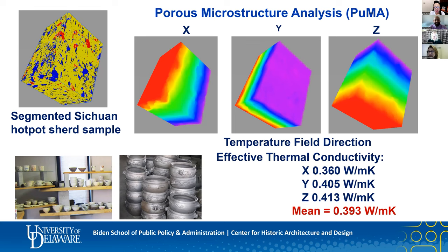One is that ancient ceramics are always going to have more variability within a production run and within a site, certainly, and even among different potters at one site compared to modern mass-produced wares made in a factory that can be very consistent. And modern ceramics also make use of various synthetic ingredients available today, whereas ancient ceramics are made with natural ingredients such as just clay and minerals and straw, that sort of thing. And also modern kilns and furnaces can achieve higher temperatures and much more controlled firing regimes than can be found with ancient firing methods.